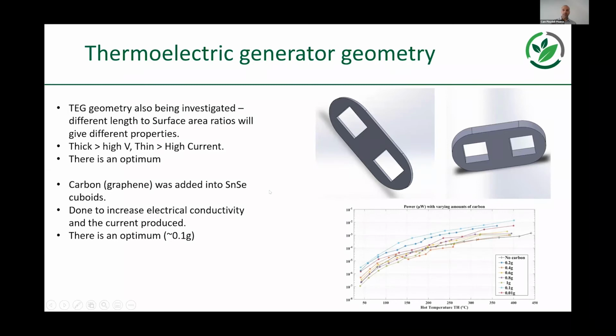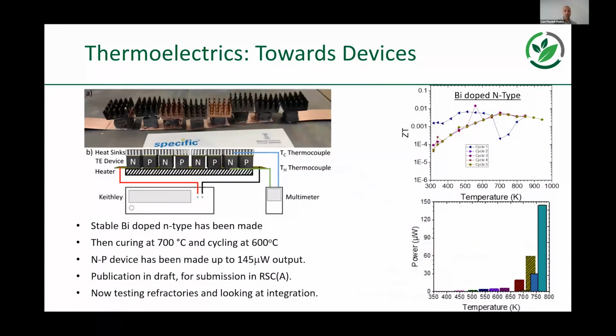And in terms of the work Geraint is doing, he's been able to optimize not only the geometry, so fat things have higher voltages but lower current, and thin things have higher current but lower voltage, but also carbon additions. Again, nice analogy to cut to refractories there, to look at how we can optimize that to improve the performance of these generators. So what's this kicked out at the end? Well, now they've been able to generate not just a P-type, but also an N-type bismuth doped material. They've put that on a hot plate, and even at the extremities, it's now producing something like about 7 times the power output of the individual legs.